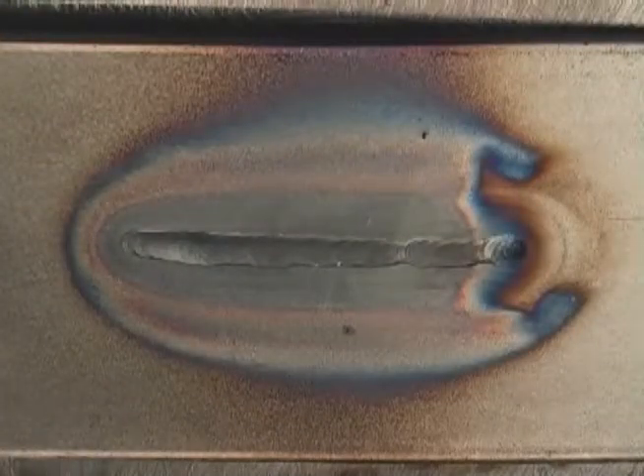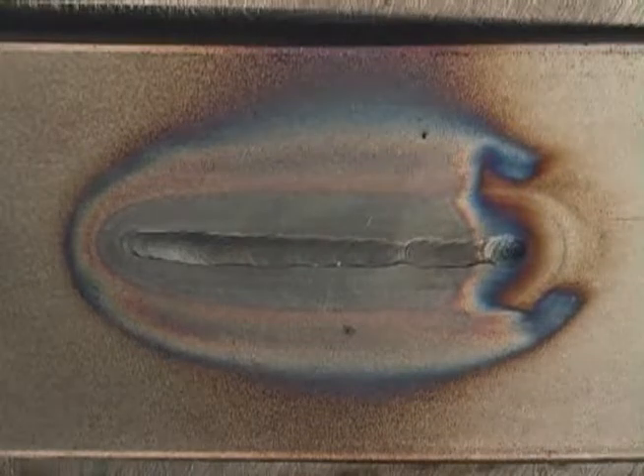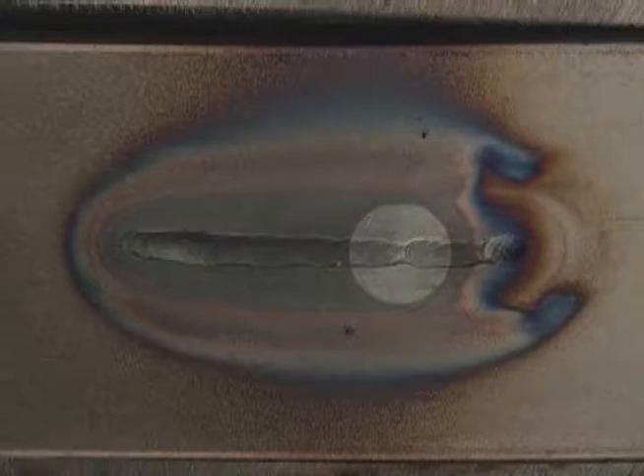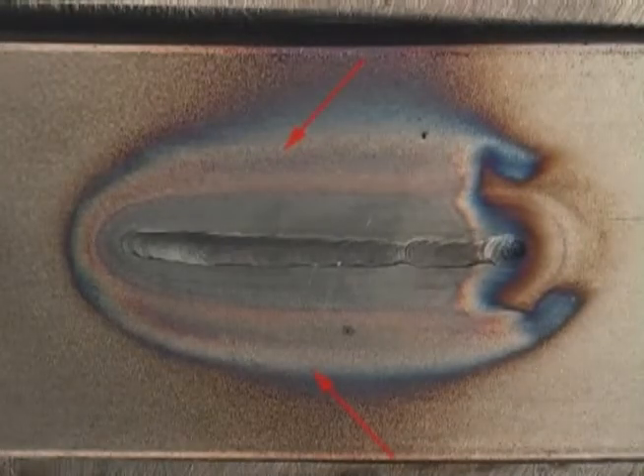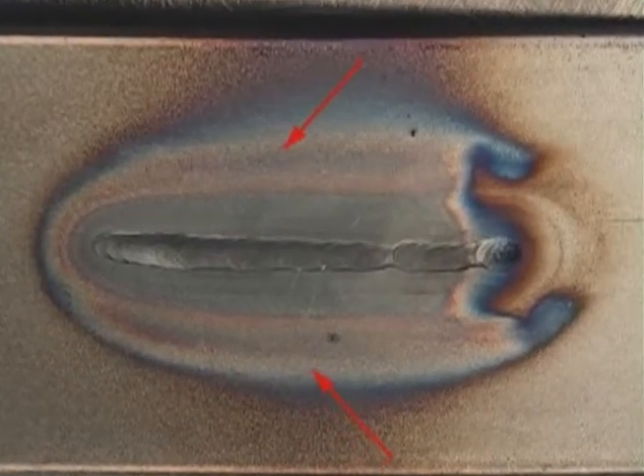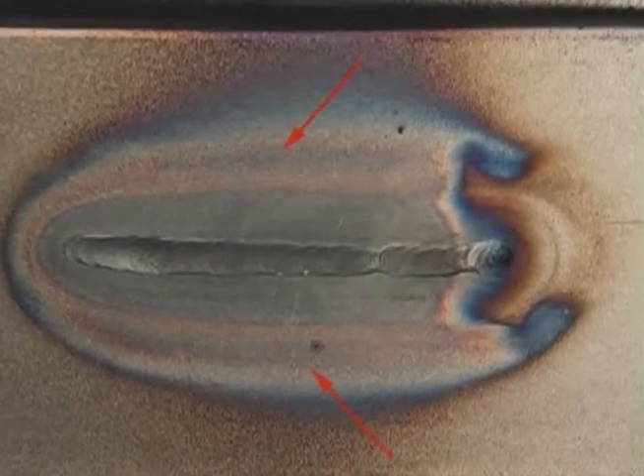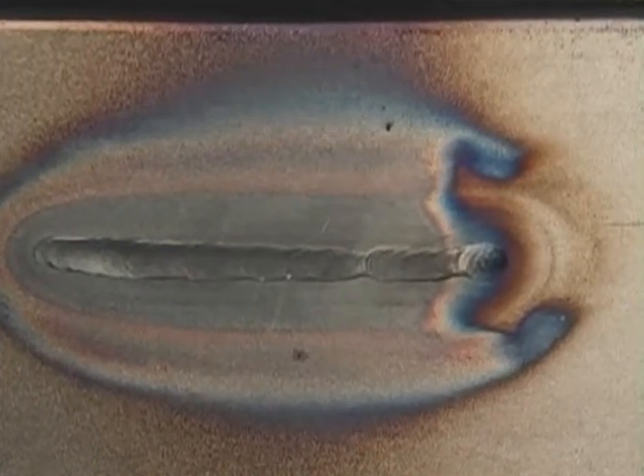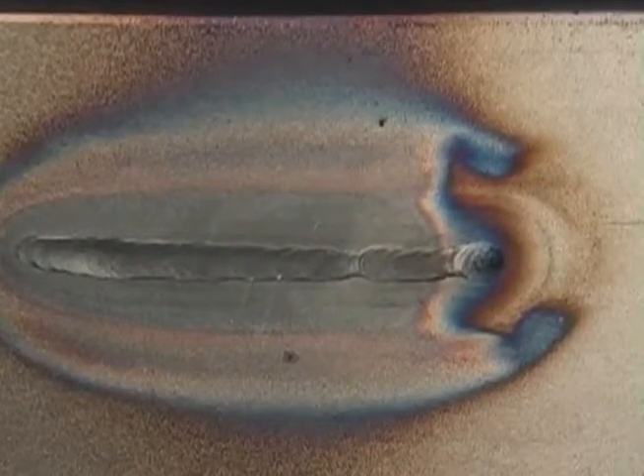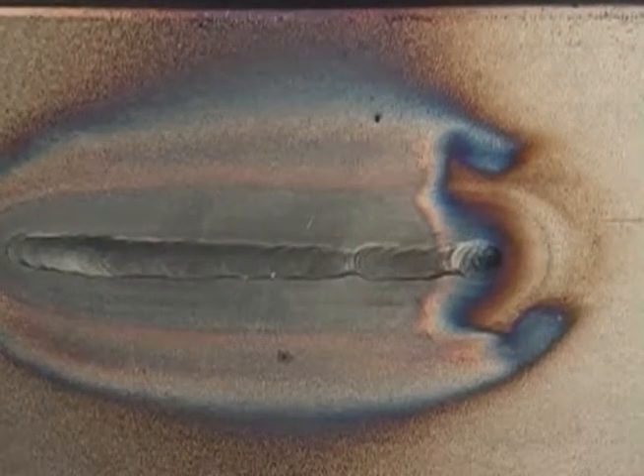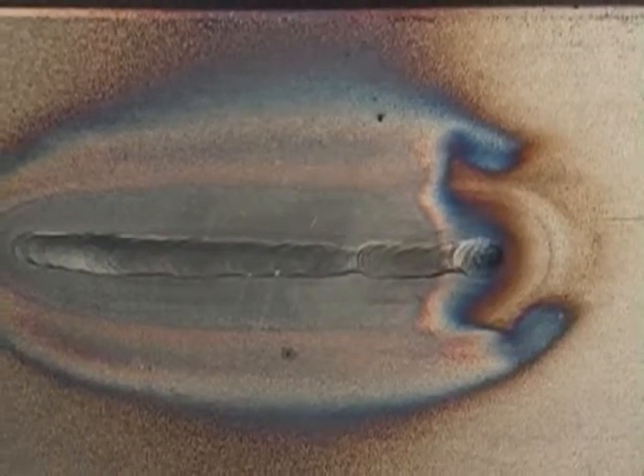Here is the finished weld. You can see the bead width is very consistent, except for the narrowing about 1/2 an inch from the end. What happened is we skipped a little, increasing our torch travel speed, causing the bead to become narrow. You can also see a very consistent heat affected zone, and at the very end you can see the effect of the post gas flow.